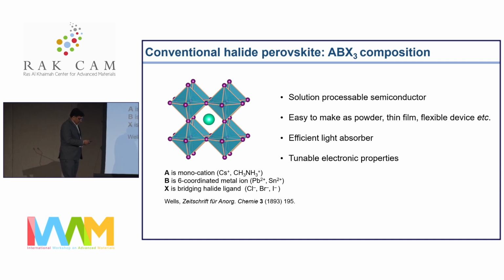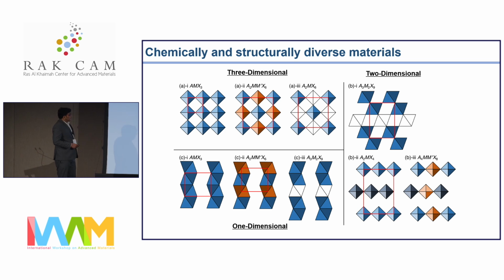Because there is a large interest, and as I mentioned, various chemical compositions have been discovered, and they relate by one way or the other to this typical perovskite which I was talking about. Some of them are double perovskites, where we use 2 types of metals or a metal and vacancy in the perovskite sublattice, and then one can reduce the dimensionality to 2-dimensional. This is the 1 1 1 or 100 type of 2D perovskite, and that can be further reduced to a one-dimensional lattice. In my talk, as I move forward, I'll be largely focusing on the double perovskites, most of which are one-dimensional or two-dimensional, and some of them will be three-dimensional.